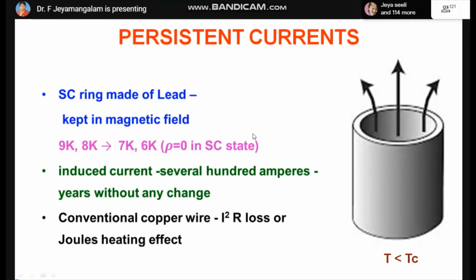In order to explain the persistent current, a material which could act as a superconductor is taken in the form of a ring. It is kept in the magnetic field and the temperature of the specimen was taken to be 9K or 8K, which is above the critical temperature for lead. And when the experiment is proceeding, we reduce the temperature to 7K or 6K so that the electrical resistance becomes 0 in the superconducting state.